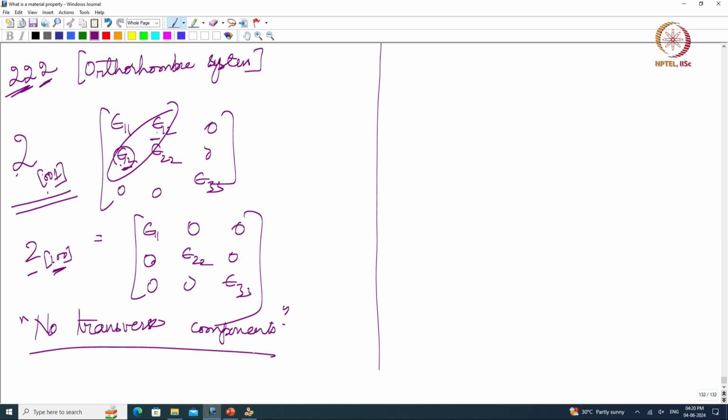As a result, you do not need to worry about Hall measurements from orthorhombic system and up. It is okay, meaning there will be other artifacts that will come up if you are not ramping up the magnetic field, but you will not have a transverse resistance by virtue of the crystal structure, right. So, orthorhombic and up,